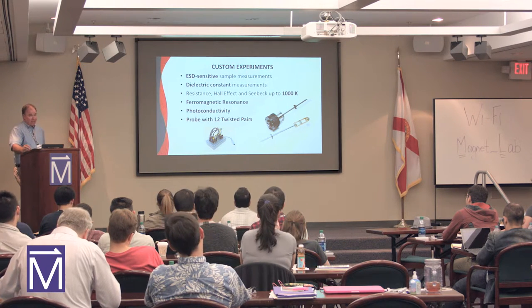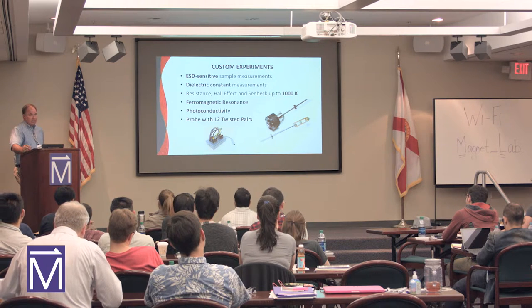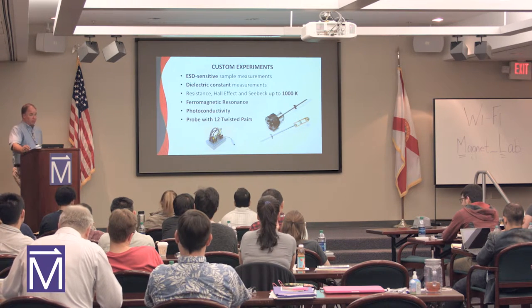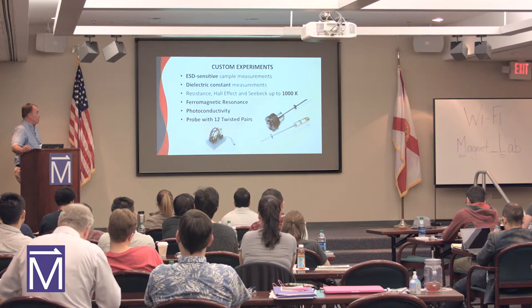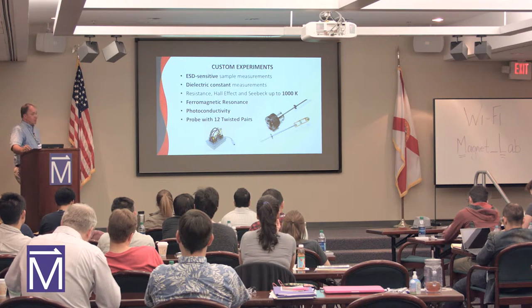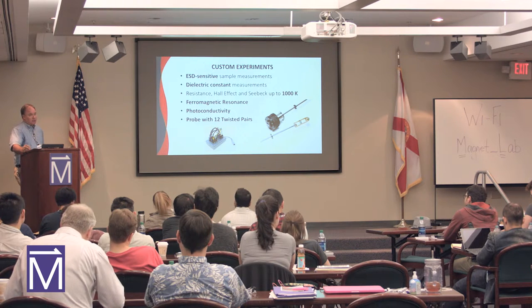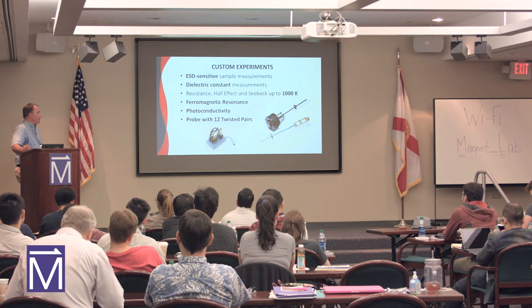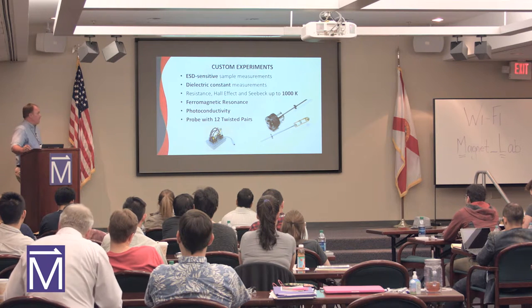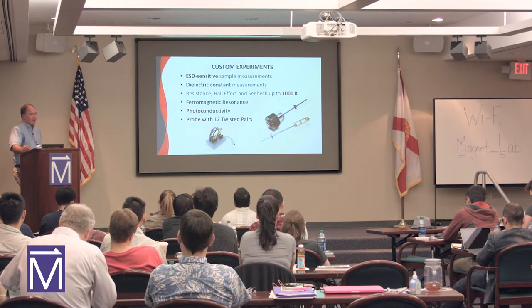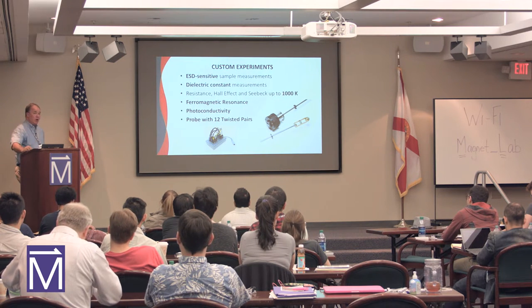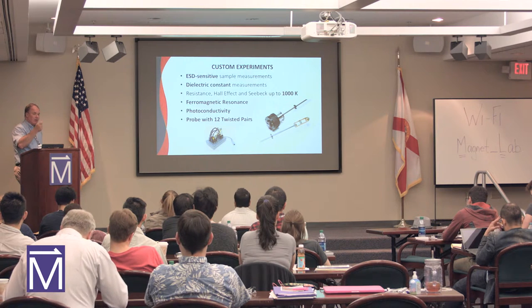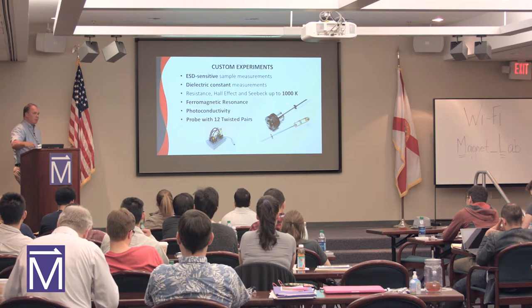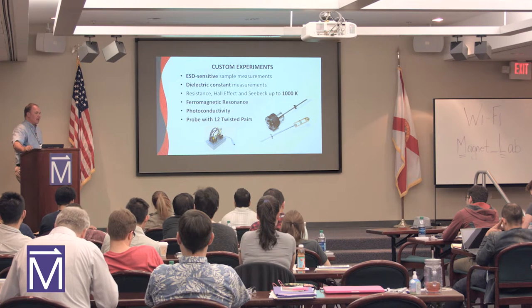We wrote an application note that describes how you can use your own probe or our MFP probe to make these measurements. We have a lot of people doing these custom experiments for dielectric constant measurements, higher temperature measurements of Hall effect, Seebeck effect to 1,000 K, and FMR, ferromagnetic resonance, so they'll put high frequency coax, supply and return coax, and have a little antenna at their sample so they can irradiate microwaves onto their sample and look at the microwave response of their sample.